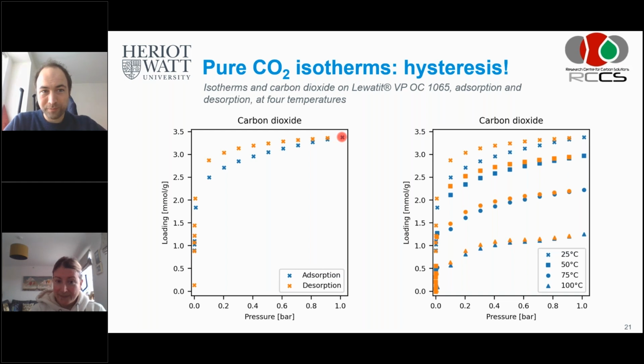But I was just curious, have you looked at the surface chemistry of the amines during the desorption process? Is that possible with any techniques? Just to get a little bit more insight about the actual species on the surface while the process occurs. Yeah, so there is limited information out there. On primary amine functionalized materials, we found one study who did in operando FTIR. They looked at the surface chemistry with FTIR, and FTIR can give away quite a lot, but it's also not per se always the most accurate.